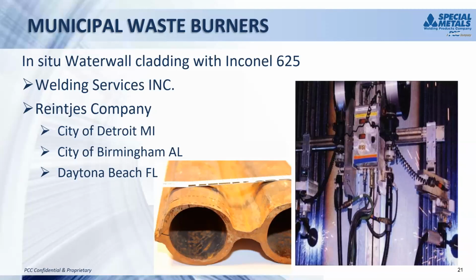The fume and the byproduct got much more corrosive. And as you can see in the picture, we started seeing very quick erosion and corrosion rates on these steel tubes that were causing some serious problems. So one of the solutions was to go back into those existing plants and just clad the entire water walls with the nickel alloy that gives much better protection compared to the steels.